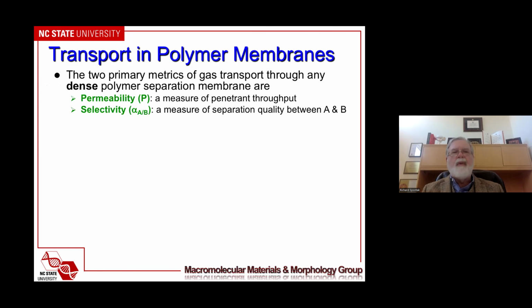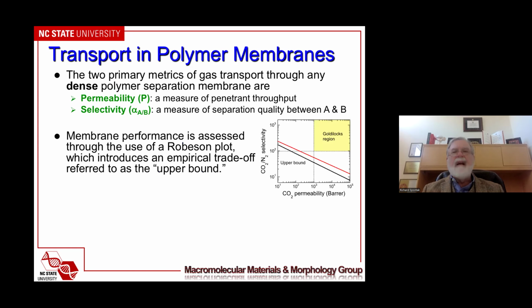So two important measurements, the permeability, which is throughput, and selectivity, which gives us a measure of separation quality. And in the simplest sense, the ideal selectivity is simply the ratio of permeabilities of the two species A and B that you see here. This is the performance graph. It's called the Robeson plot. And on this, we plot on double logarithmic coordinates the selectivity of CO2 to another gas, and we choose nitrogen as a mimic for air.